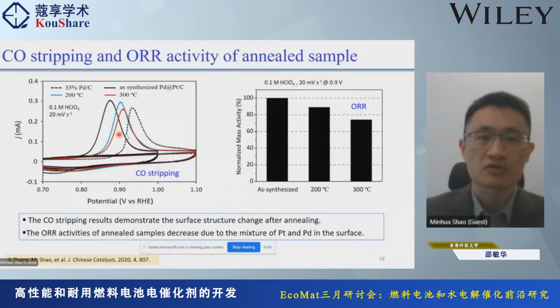Okay, so that means the surface composition has already changed from pure platinum to a mixture of palladium and platinum. And the activity change is also very clear. Okay, after annealing, the mass activity will drop. For the 300 treatment sample, the activity dropped by 30%, so a significant activity drop.